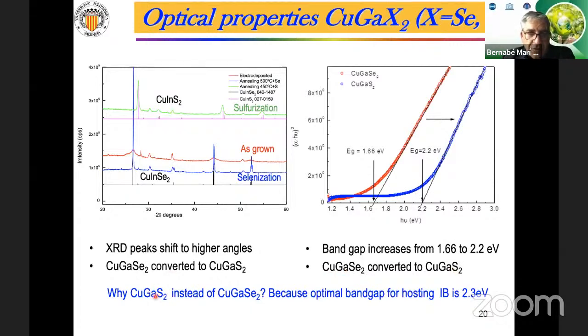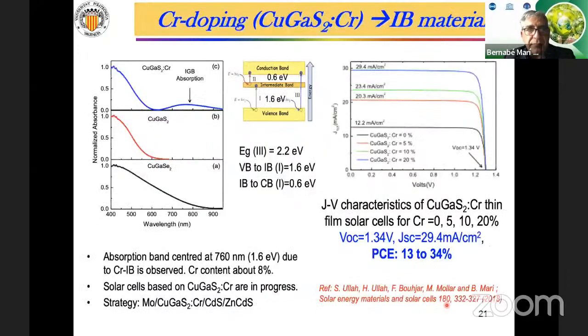Why do we use copper gallium sulfide instead of copper gallium selenide? Because the optimal gap for hosting an intermediate band is 2.3 electron volts. This is why sulfur is required.